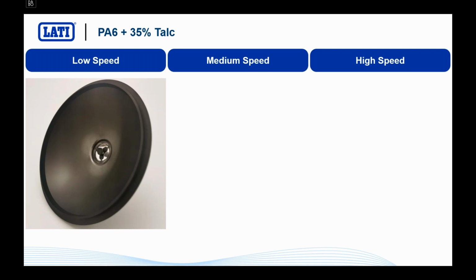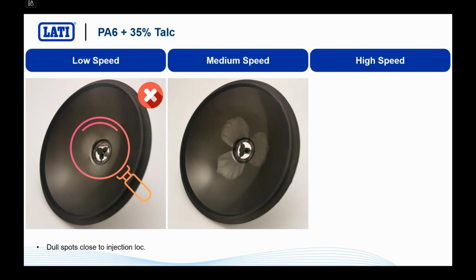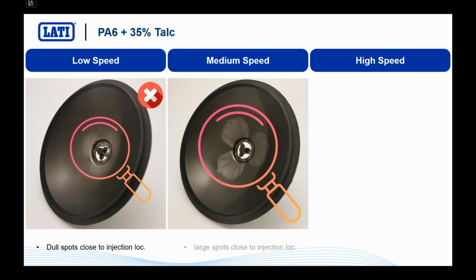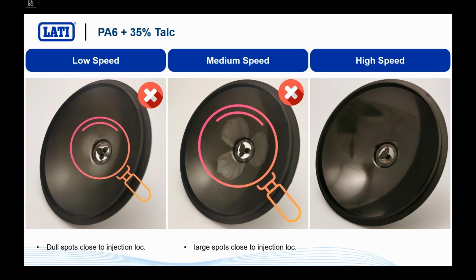Let's see the same from below. Also in this case, you see the same trend. So you see a much worse looking surface, which becomes dramatic in the case of a medium injection speed, and they disappear, or I would say they more or less disappear when it comes to higher speed. But please look how you still have some kind of sign here, you have a sign here, you have a sign here. So something is different between the fan gate and the 3 submarine gate. Pay attention, because this is absolutely something to keep in mind. Anyhow, the situation has been vastly improved by increasing the speed.